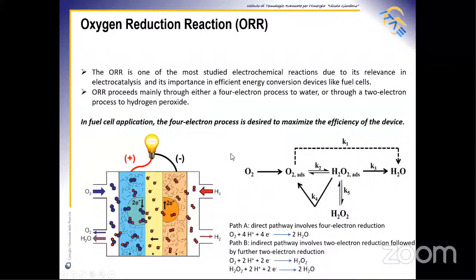The oxygen reduction reaction is one of the most important reactions in devices like fuel cells and batteries. The oxygen reduction reaction generally proceeds either in a direct pathway involving four electrons from oxygen directly to water, or by an indirect pathway involving two-electron reduction with the formation of hydrogen peroxide, and a further two-electron reduction with the formation of water.